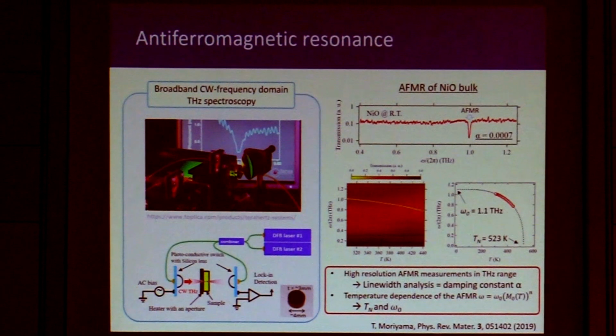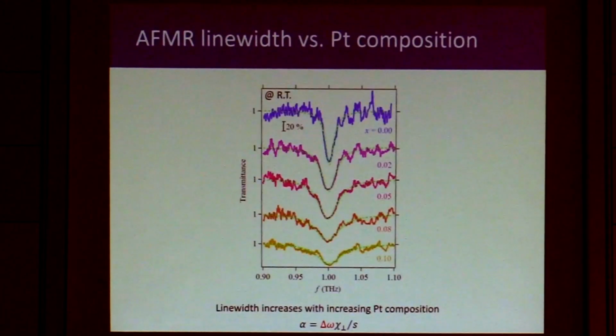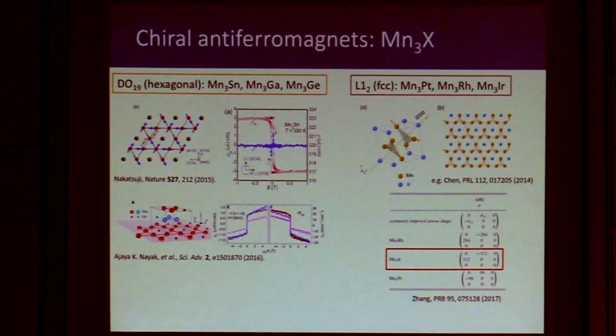What is the mechanism for the anomalous Hall effect in this antiferromagnet here? And what kind of moments are switched by the magnetic field during your measurements? Okay. It's very similar to the manganese 3 tin case, where we just switch the chirality of this triangular magnetic lattice. Depending on this chirality switching, we can have the anomalous Hall resistance change.